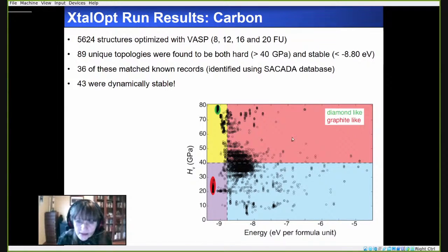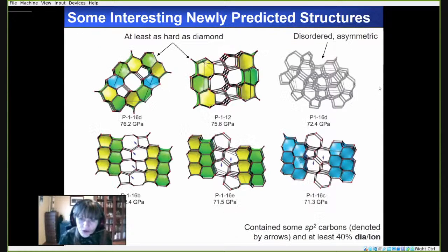And we analyzed the phases in the yellow quadrant, found that 36 of them matched previously predicted or synthesized records, and 43 of them were unknown phases that were dynamically stable. Here I show just a couple of the phases that we found that were novel. And we classified them according to little bits. The blue bits are related to diamond topologically, and the yellow and green bits are topologically related to Lonsdaleite, which is a form of hexagonal diamond. So most of these very hard phases were composed of little bits of diamond or Lonsdaleite.